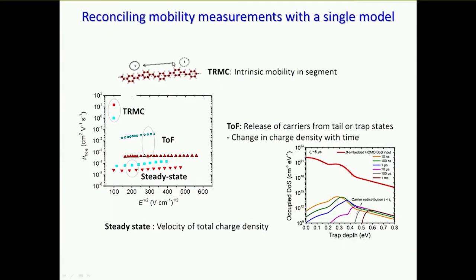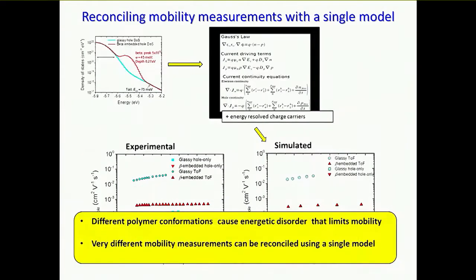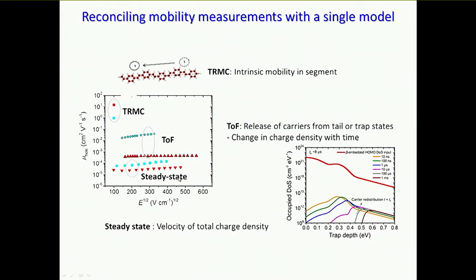Okay, so we were here, and then the difference between, if you like, the time of flight case and the steady state case is that in the one case, you're effectively looking at the change in charge density as a function of time, and so you're very strongly sensitive to the emptying of traps, and that introduces a large difference in the effective mobility. And in the steady state measurements, you're more looking at the average velocity of the charge carrier population, and in that case, the traps are a penalty, but not such a great penalty.